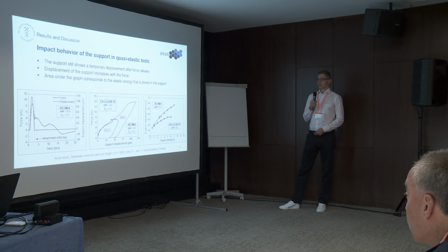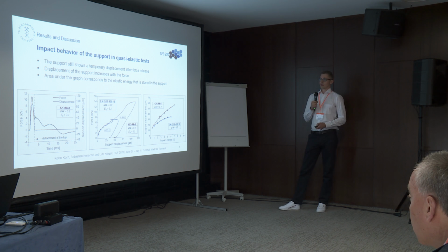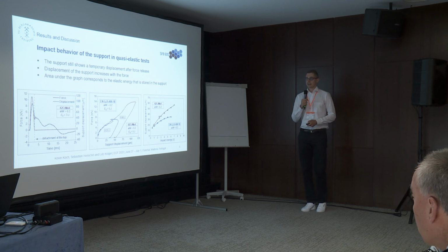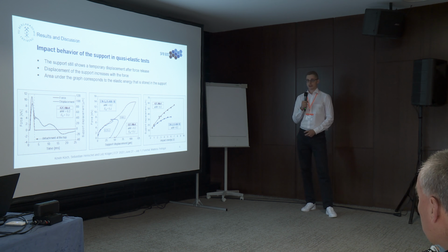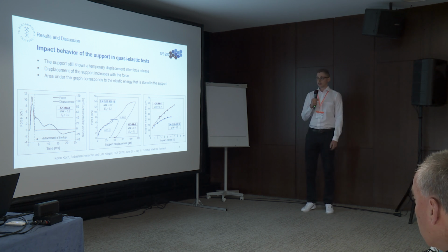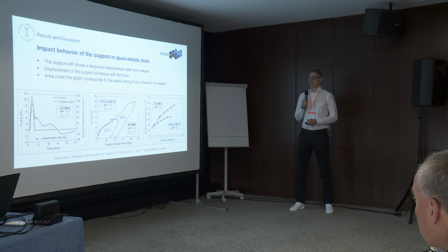So first, we investigated the behavior of the support in elastic tests. We recorded our force and our displacement of the support over the time, and we could see that first the support still shows a significant displacement after the test, and also that for both materials the displacement increases with our force.